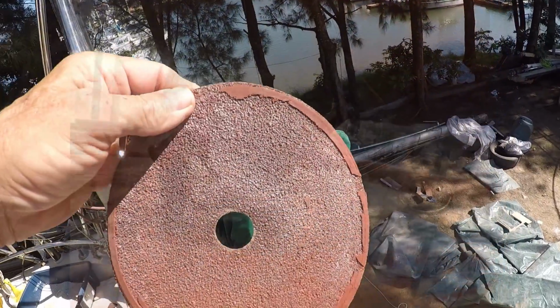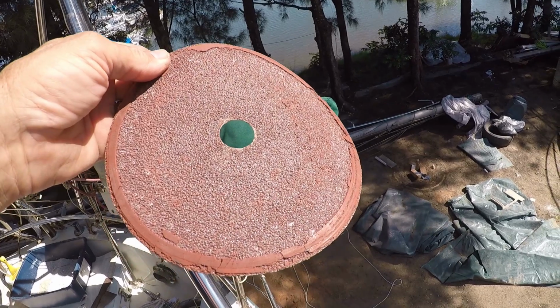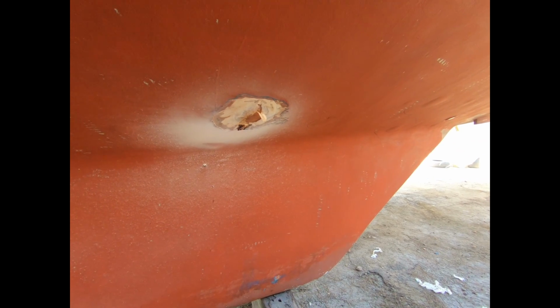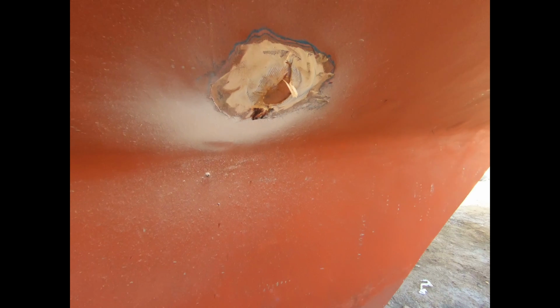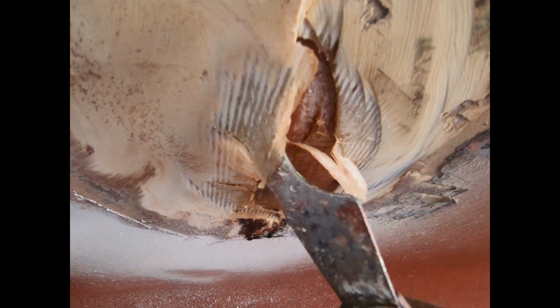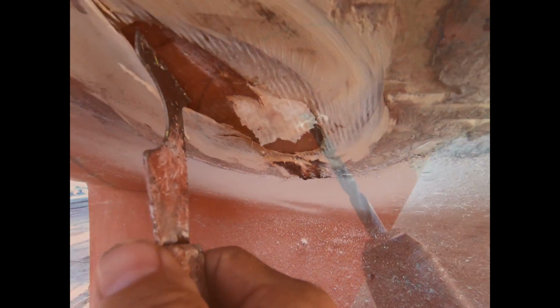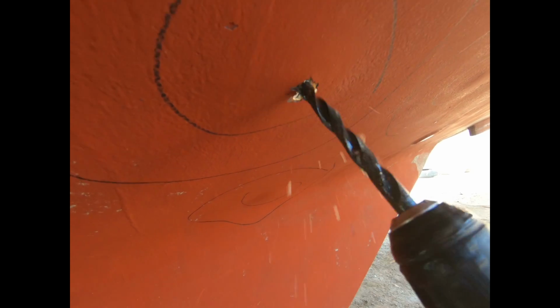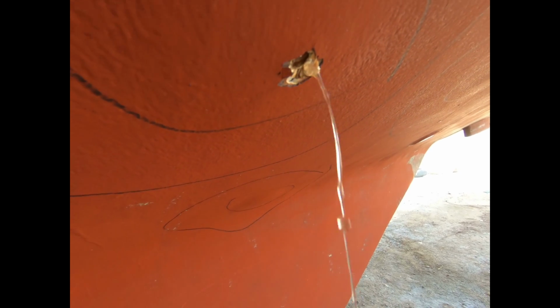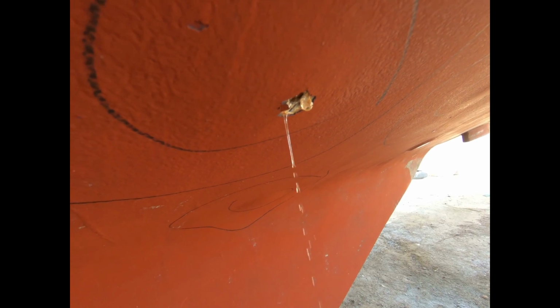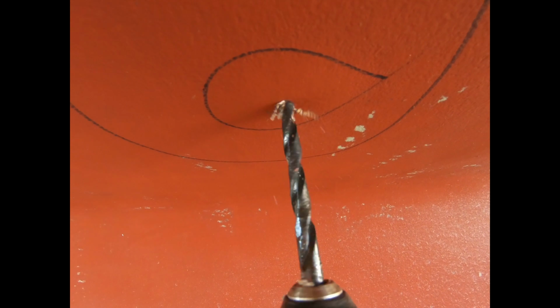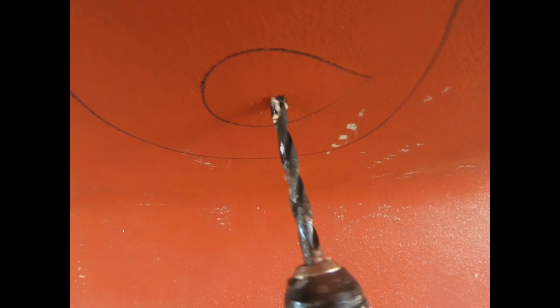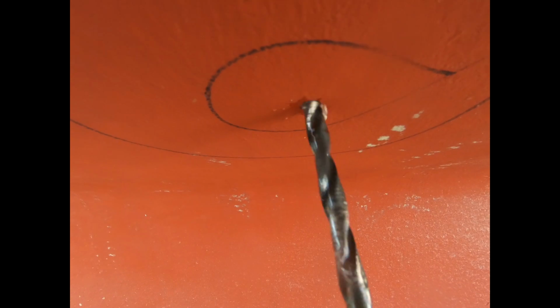Digging into these resin blisters below the waterline where there's a lot of soft anti-fouling paint just wasn't working out so well. We opened them up a bit, but there had to be a better way of digging out the fiberglass that was delaminated from the hull. And that's where we found it was better to first drill holes into these blisters, and if there is moisture, which oftentimes there was, to let it squirt out. Although it might look clear here, generally the liquid was more of a dark tobacco looking color.